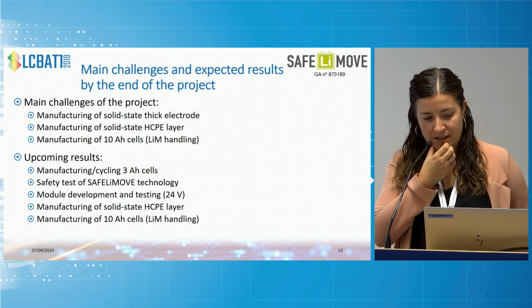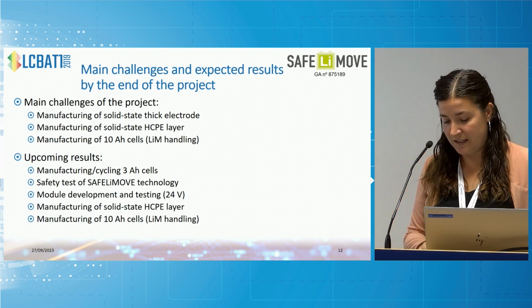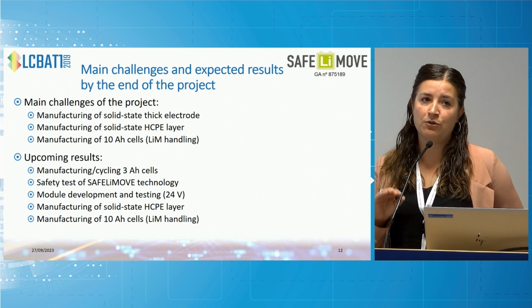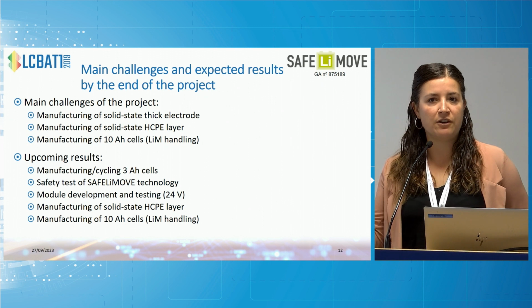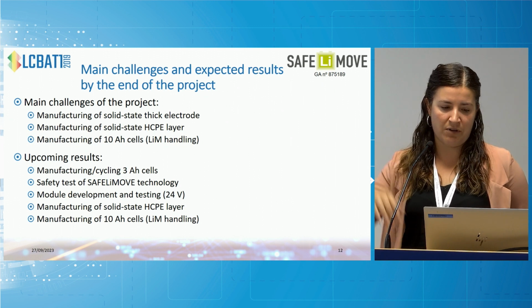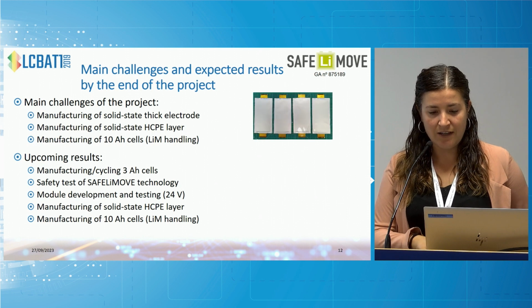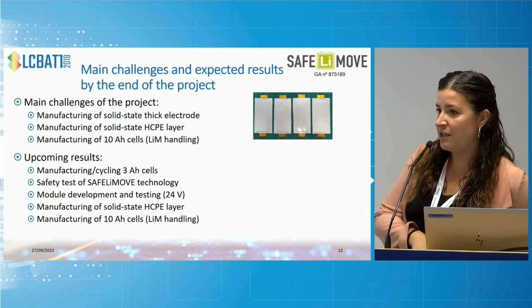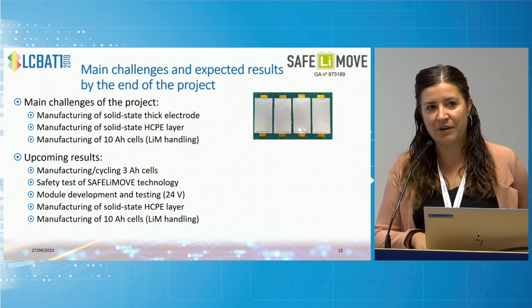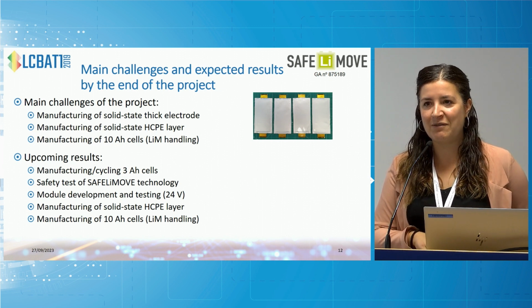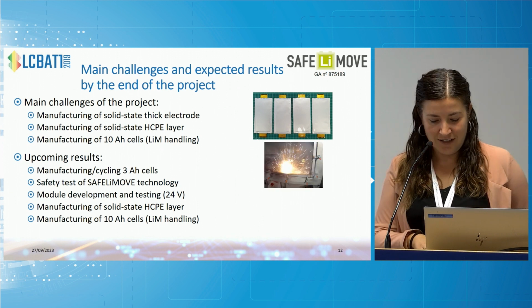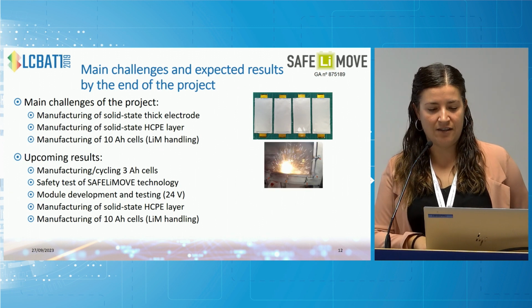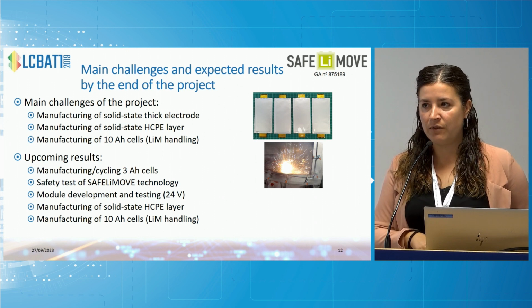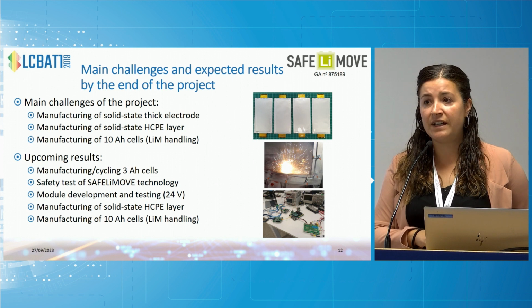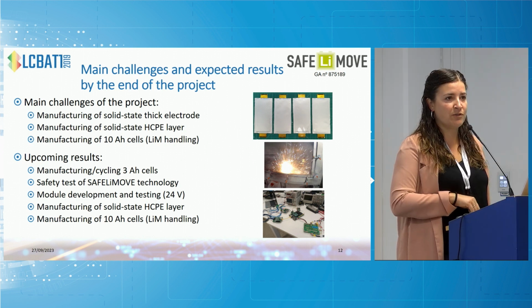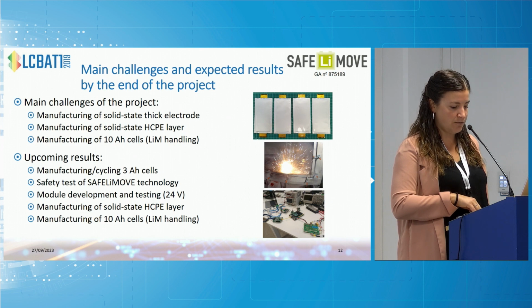for that reason, the upcoming results that we will have are going to be related to the cycling of 3 ampere-hour cells. So in order to be on the safe side and guarantee that we are able to scale up the technology from 1 to 3 ampere-hour cells, we decided to decrease the capacity a little bit. Cells have been manufactured already by SAFT and have been shared with the partners in charge of the cycling, so I hope to have some results soon in this regard. Also, safety, led by CEA, will be tested in this new generation of 3 ampere-hour cells. And also Ikerlan is working on the module design and on the validation.